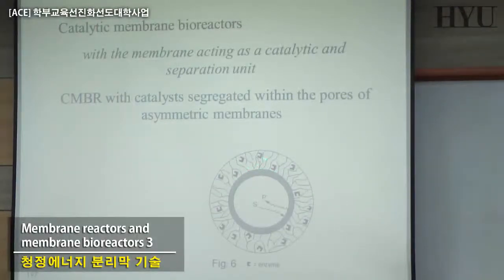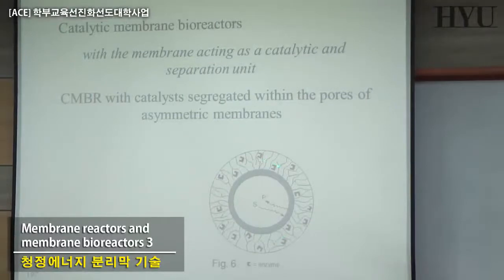This is a system in which we have been immobilizing the enzyme. In this case, the dense skin of this asymmetric membrane is inside. So what you do is ultrafilter a protein solution from outside to inside, so the protein cannot penetrate across the dense skin. The water, the solvent, is going through. So what is happening at the end of the ultrafiltration of this nice hollow fiber module is that you will have all the spongy part of your membranes filled with the protein.